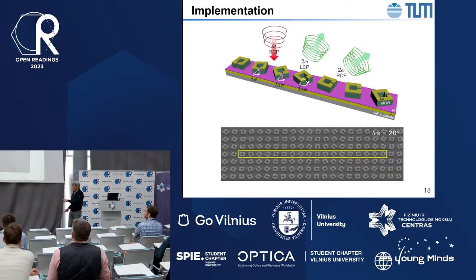And then the second harmonic output is a similar effect. So by rotating these resonators, we delay the second harmonic phase, so this one emits second harmonic, this one emits second harmonic with a phase delay, and this one emits second harmonic with additional phase delay. How much is the delay? The delay is dependent on the angle of rotation. So the phase delay, if you have right circularly polarized input and right circularly polarized output, one degree of rotation will lead to 3 degrees of phase delay. If you have right circularly polarized input and left circularly polarized output, 1 degree of rotation will lead to 1 degree of phase delay. So 3 times the angle or 1 time the angle.